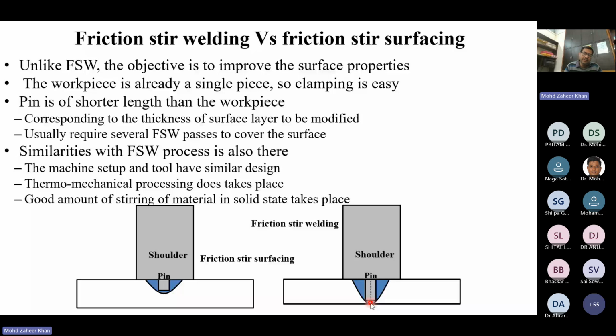In the case of friction stir surfacing, as the name suggests, we are only interested in changing the properties of the surface of the material. So what we do is take a tool where the pin length is very short. The pin length is only equal to the thickness of the surface layer of the material that has to be modified. So the pin is shorter in length than the workpiece. Correspondingly, the thickness of the surface layer can be modified depending on the length of the pin that we have chosen. There are several similarities. The same setup and tool can be used for surfacing also, with the change that the tool design has to be changed, and the pin has to be made shorter in length.